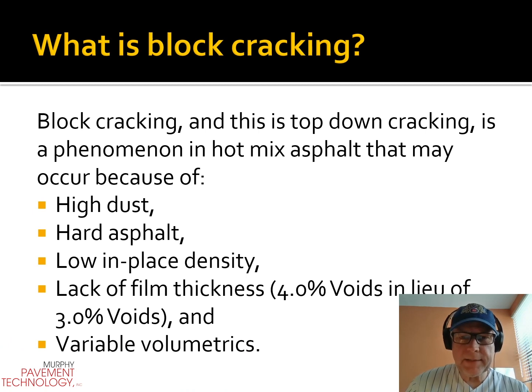Block cracking is when asphalt's too hard, usually has a real high amount of dust. Hard asphalt, liquid asphalts, we need to use a softer brand, low in-place density, a reduction in film thickness, and sometimes people use an excessive amount of recycled materials in the asphalt, which, if not properly designed for, can dry the mix out as well, harden the asphalt, and provide a lot of minus 200 or dust, which again stiffens the asphalt. So get a good design first again.